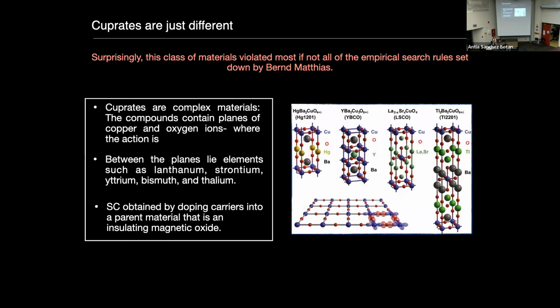Now, cuprates are just different. And all of the rules that I told you that Bernd Matthias had postulated and that were very successful for him in finding new superconducting materials basically break down here. First of all, cuprates are complex materials in terms of their structure. You can see here the crystal structures for quite a few different cuprates. So you can see that in all cases we have copper oxygen planes. The copper is here in blue, the oxygens are in red. This is just a zoomed in version of one of those, where the copper has basically a square planar environment of oxygens. And again, this is common to all of the cuprates that you see here.